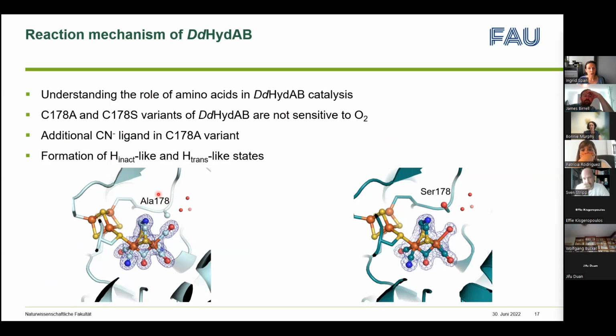And interestingly, they are also not sensitive to oxygen. And we see in the C178A variant that we have a diatomic ligand. And we have also more data that supports an additional cyanide ligand in this active site. And we also have a structure of the serine mutant, but the spectroscopic data are not very clear, and we modeled a water because we're not sure what this monoatomic ligand is. But yeah, we're still working on this. And for the C178A mutant, we proposed the formation of Hinact-like and Htrans-like states.